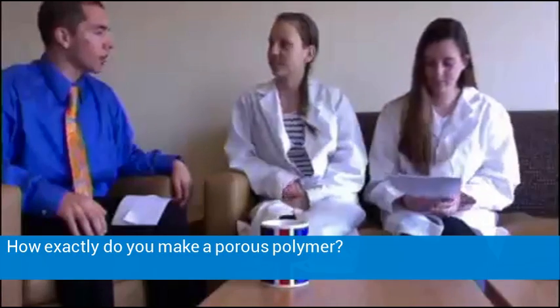Of the new joint. After some weeks, the pores of the prosthetics start to get filled with the new bone, and the bone tissue would start to grow around the prosthetic. The growth process takes between months and a year, but in the long run, it's very beneficial for comfort at the attachment site. So how exactly do you make a porous polymer?